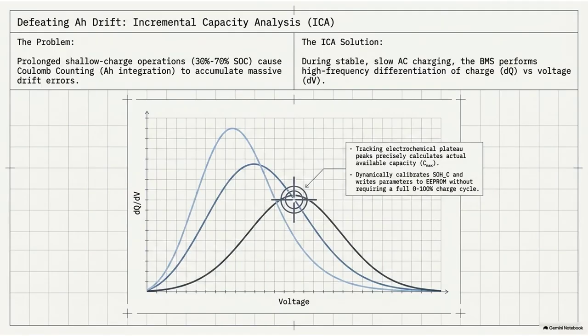Exactly. By taking the derivative of that charging curve, the ICA algorithm transforms those flat electrochemical plateaus into sharp, highly visible peaks on a mathematical graph. That's so clever. It is. The magnitude, the area, and the specific voltage locations of these peaks act as a distinct chemical fingerprint of the active material currently available in the cell. It's essentially performing a non-invasive MRI on the electrochemistry while you charge in your garage.